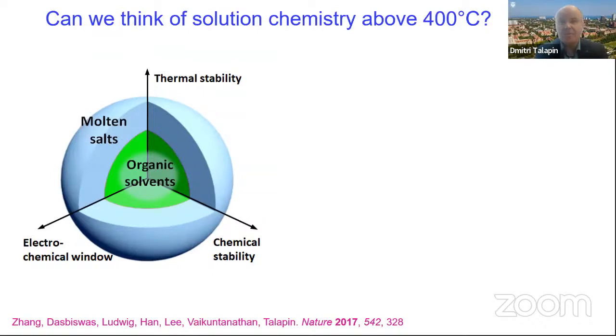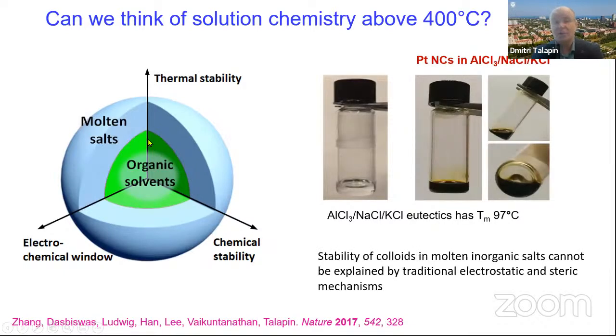And that led us to think about possible solutions to this problem. If we can make phases by solution chemistry that require high temperatures, probably the most thermally stable solvents I can think of would be molten inorganic salts. So we started playing with molten inorganic salts as solvents for doing colloidal chemistry several years ago. And to our surprise, these were, to the best of our knowledge, the very first demonstrations of colloidal stability in molten salts.